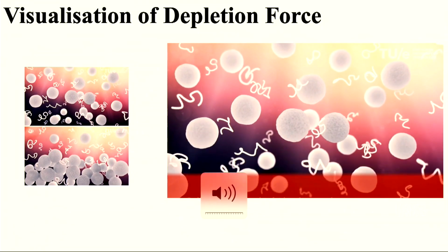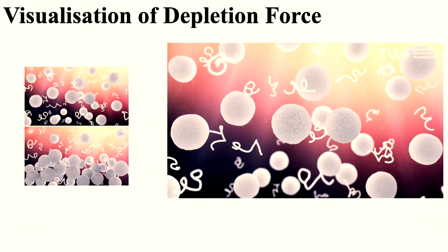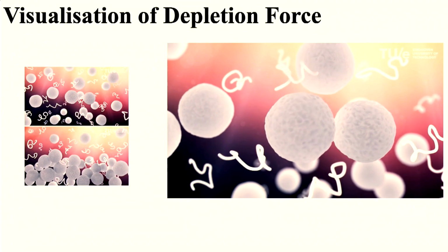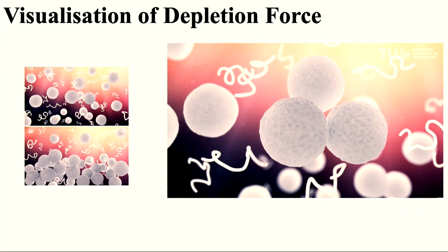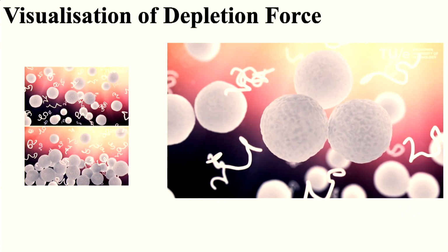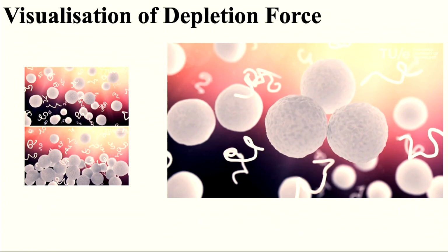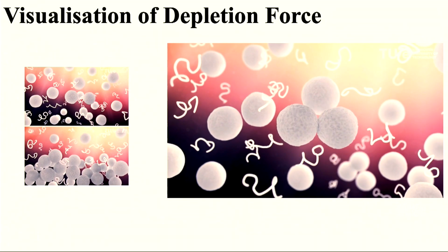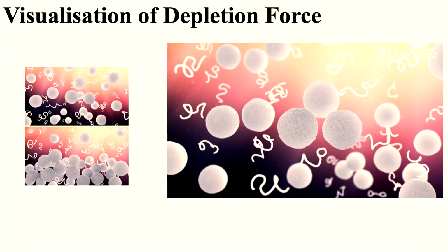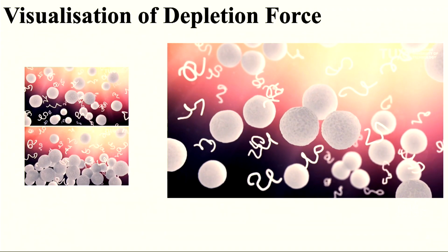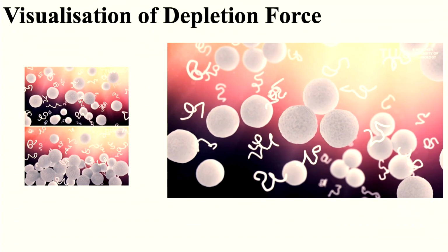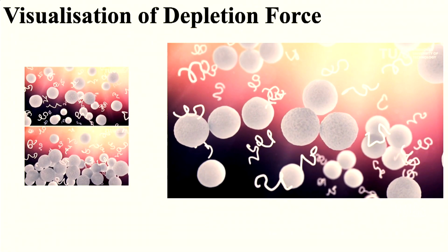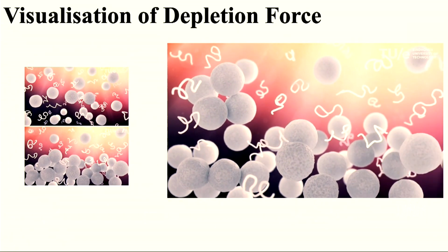Daily life products such as food and paint are mixtures of colloids and polymers such as proteins, latex particles and polysaccharides. Exclusion of the polymer chains from the colloidal particles results in effective depletion layers. Overlap of these depletion zones induces an indirect attraction between the colloids. Above a certain polymer concentration, this leads to phase separation into a colloid-rich and a polymer-rich phase.